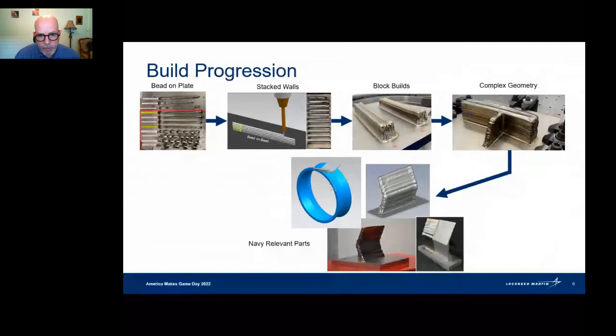Essentially, what we've done is we've had a fairly determined build progression. When we initially started this project, we laid down simply bead on plate. We didn't even try to build upon the laid down beads, just to try to get a better understanding of the process control itself, and what the process windows look like. What our schedule parameters, I mentioned those 4 different control parameters, what those parameters look like and what they produce within a given boundary. So we use that to get a reasonable approximation of what a good set of schedule parameters would be.